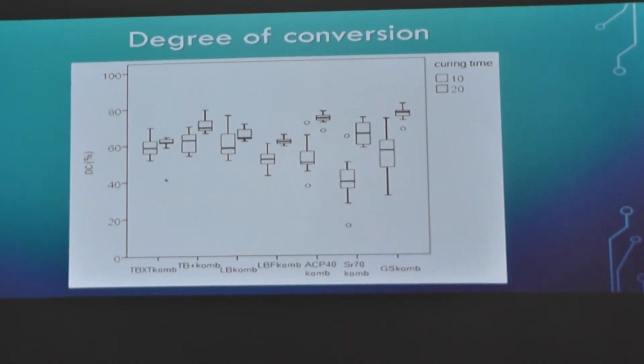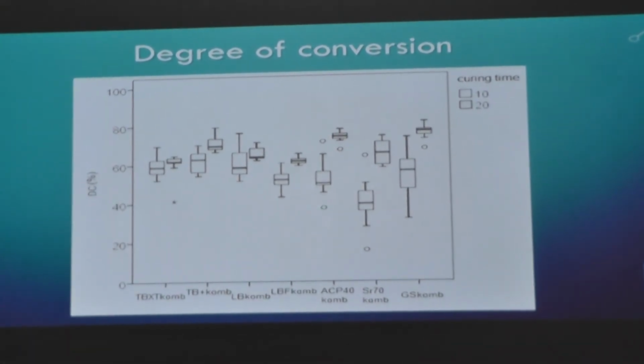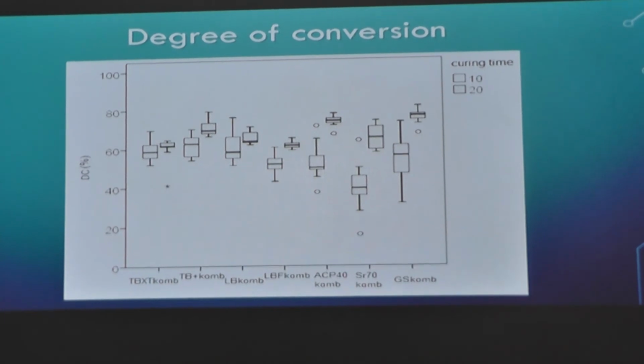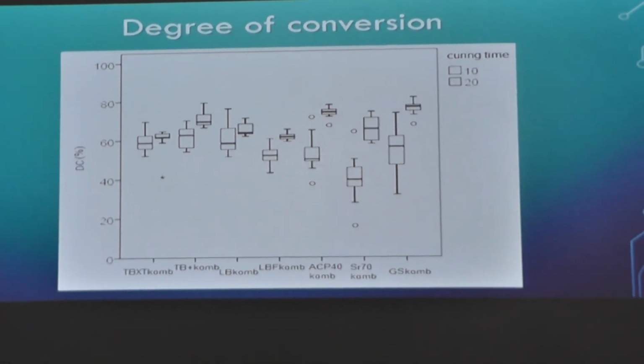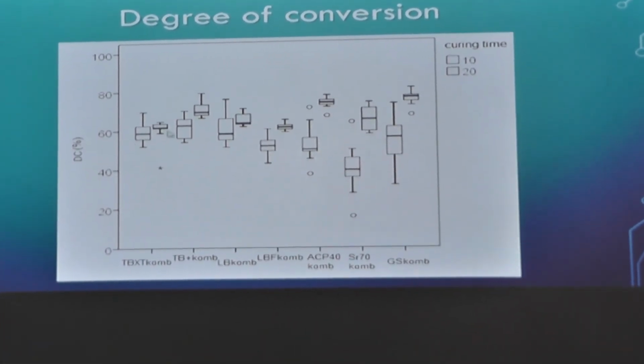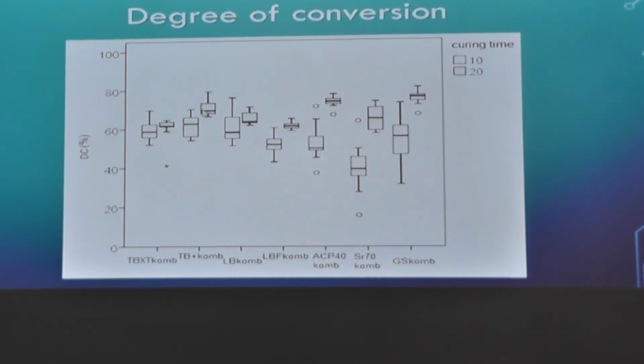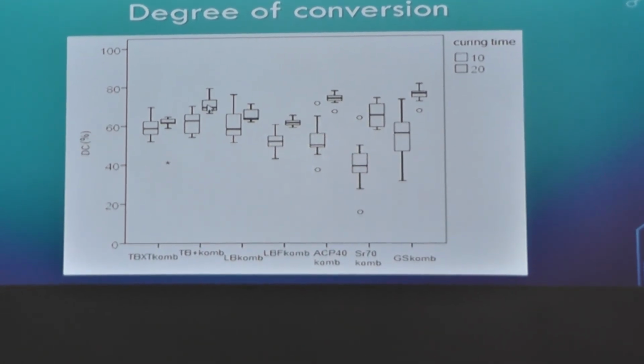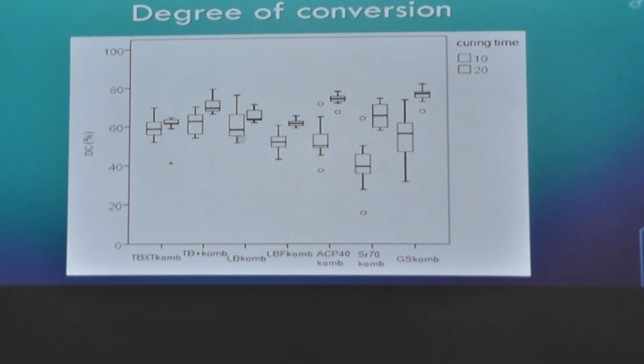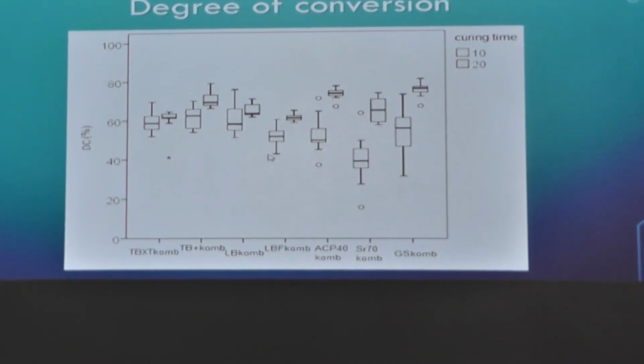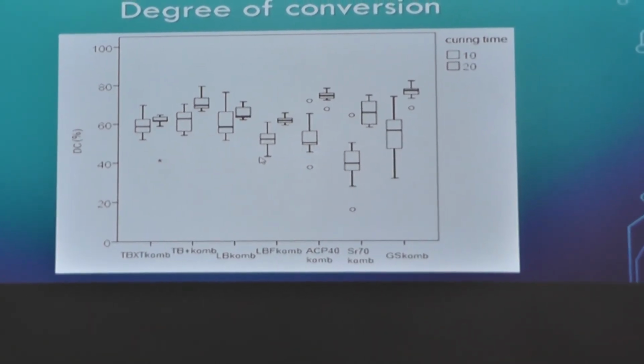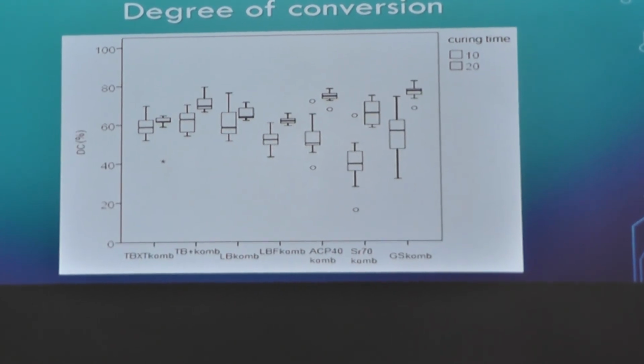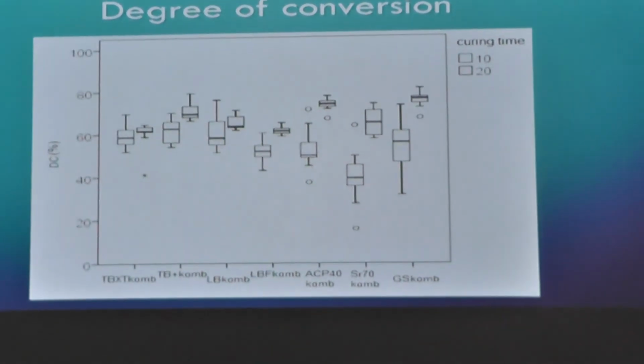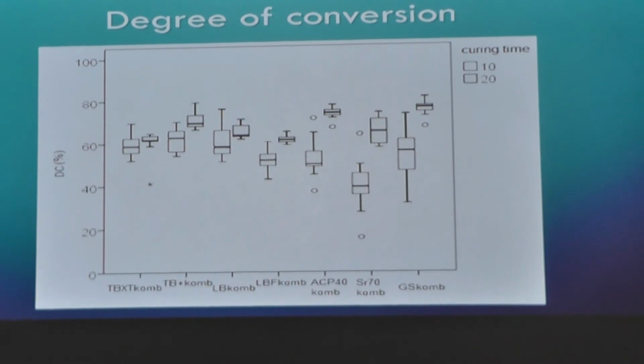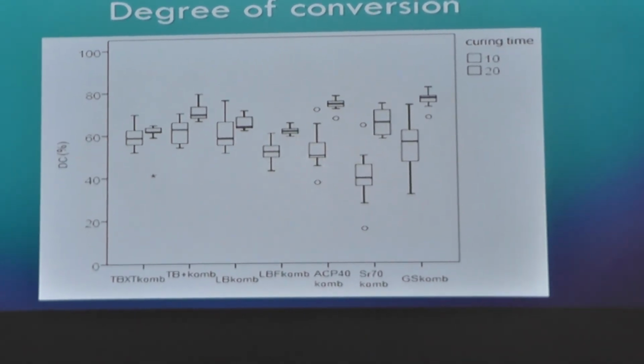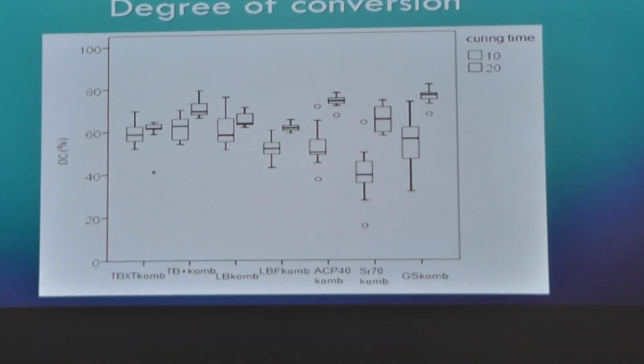So 10 seconds for Transbond is enough, but do it in 5 seconds from each side from an angle. If you use all these others, so even Transbond Plus, the degree of conversion is significantly higher if it is cured for longer, and for all the other materials like Light Bond that we used down here also, it should be cured for longer, even though they say in the instructions curing for 10 seconds is enough. And this is all with a high power LED lamp that we also use here.